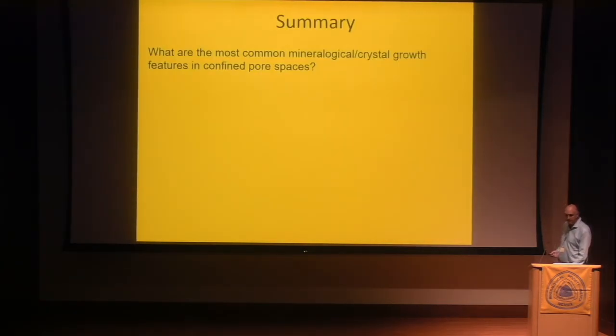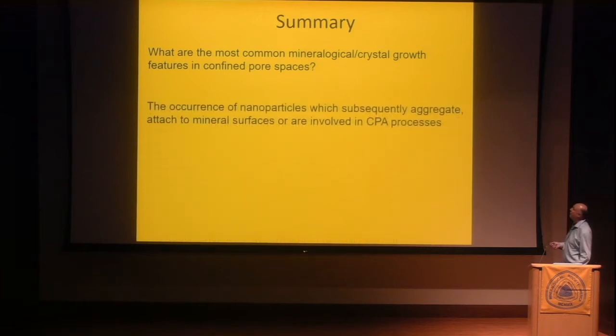So what are my summaries regarding mineralogical processes? What are the most common mineralogical or crystal growth processes we have so far observed in confined pore spaces? One of the most common features is that we observe incidental nanoparticles. I mean, you would say, okay, there are nano-confined pore spaces, obviously there have to be nanoparticles, but what we didn't expect is that those nanoparticles aggregate, that they agglomerate, that they attach to mineral surfaces, or that they are actually involved in crystal growth processes.